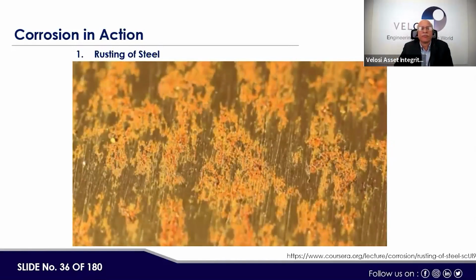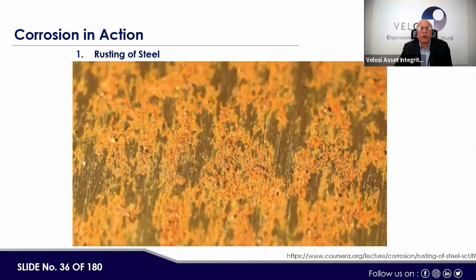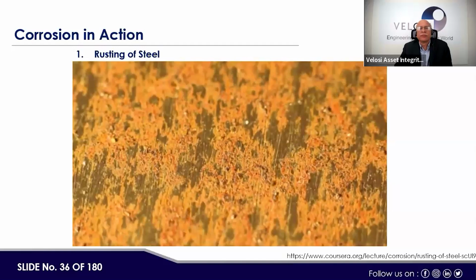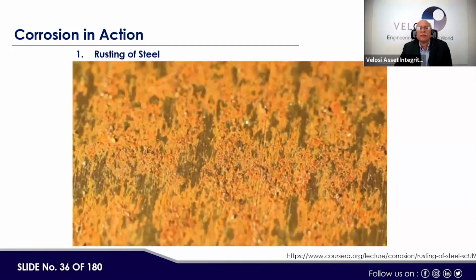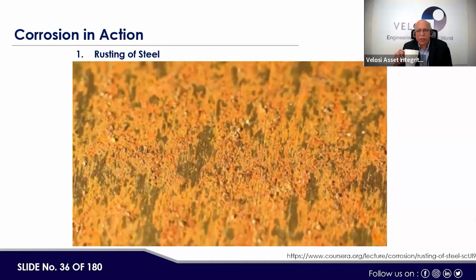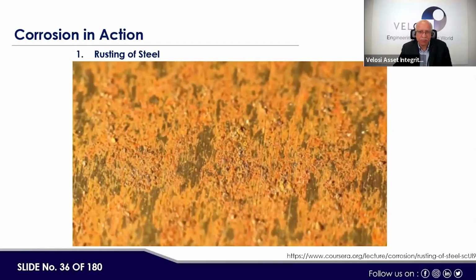As time progresses, the rusted areas extend gradually in a filamentary manner, often following the direction of the grinding marks. This is known as filiform corrosion and more usually occurs underneath paints and coatings. The head of the filament contains corrosive fluid or electrolyte which forms after sea salts fall onto the metal surface during the atmospheric exposure. Sea salt mainly consists of sodium chloride, which dries as cubic crystals. Some salt deposits can be seen as small squares on the rust after the exposure.